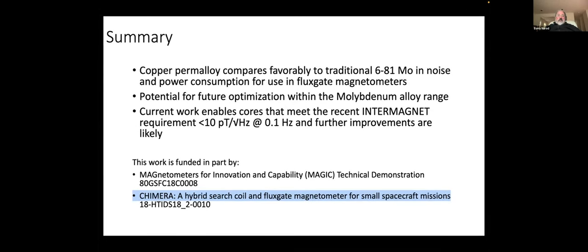There we go. So to summarize this part of the presentation, the copper permalloys, as we have now found them, compare very favorably to the traditional 6% moly permalloys that were in the legacy materials, and even compared to 6% moly permalloy ring cores that we have made ourselves. We're not done. There is potential for future optimization within the molybdenum alloy range and still within the copper alloy range. We haven't exploited, I think, yet the best possible alloys. We have more work we need to do on these, but certainly getting to 3-4 picotesla per root hertz at 1 hertz, and say 5-6 picotesla per root hertz at 0.1 hertz, is already a done deal.